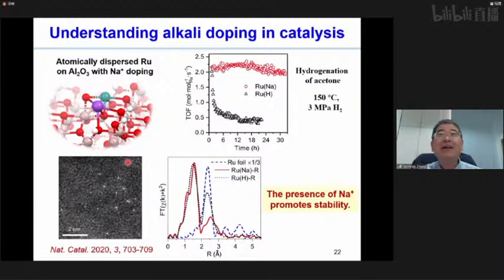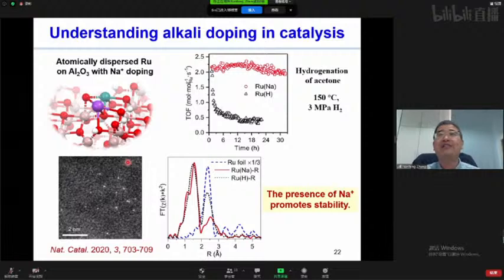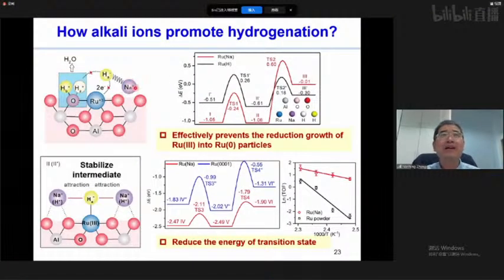So ruthenium +3 is the active site for this reaction. The main reason why the sodium can stabilize this atomically dispersed catalyst is that we have strong coordination of this sodium cation with hydrides on ruthenium +3. And this interaction actually can stabilize this hydride species. What's even more interesting is that, besides preventing the reduction and growth of ruthenium +3 into ruthenium zero, we also found that this interaction can reduce the energy of the transition state of the hydrogenation reaction.